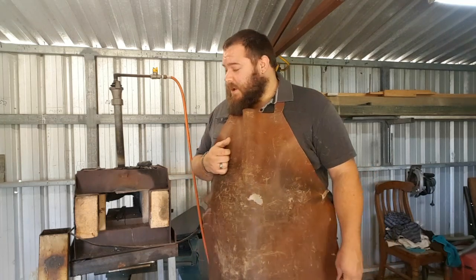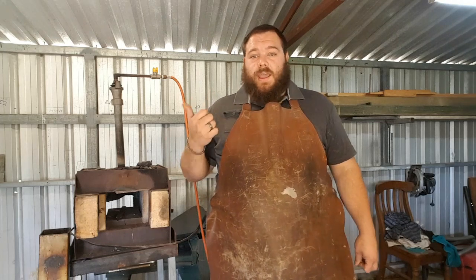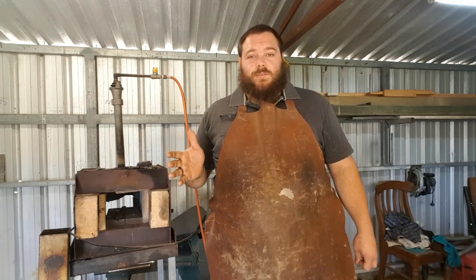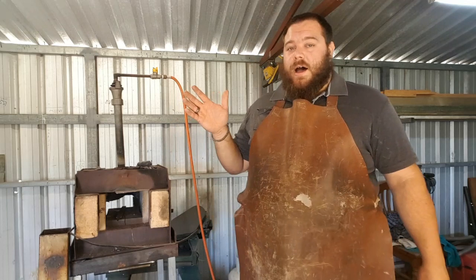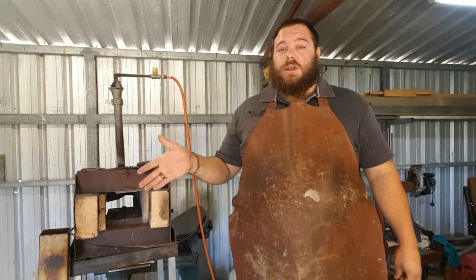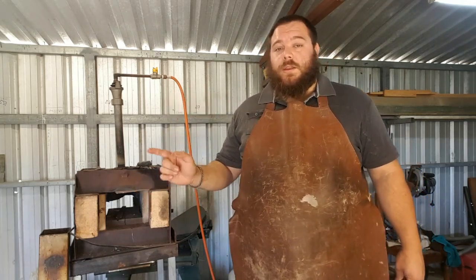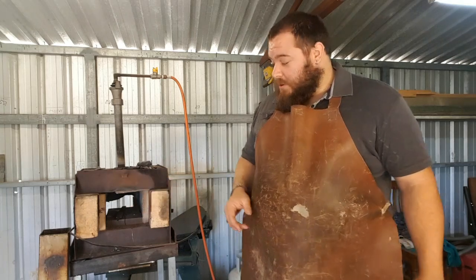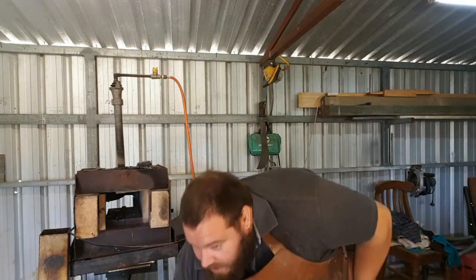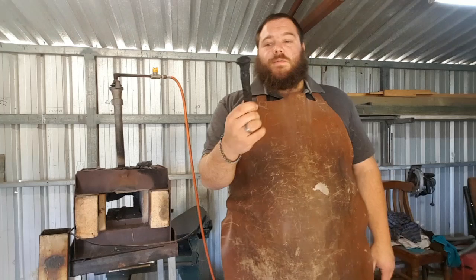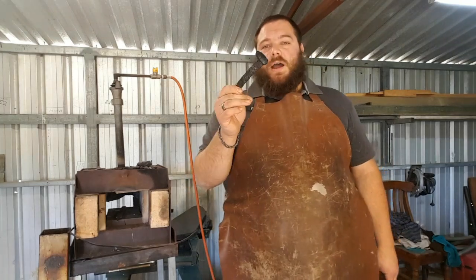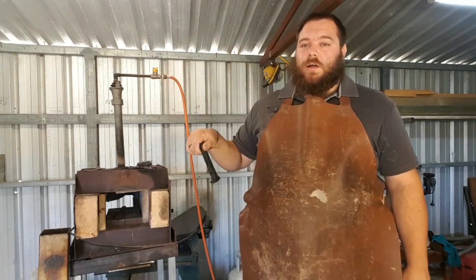So, the next step, we're going to heat it up to critical temperature, just past critical temperature, into that hardenability range, and then we're going to quench it in oil. But before we do that, we're going to preheat my oil, and all I'm going to do that is I've got a very old and dirty railroad spike. I'm going to heat this up to a bright orange color and dunk it in there, swirl it about.